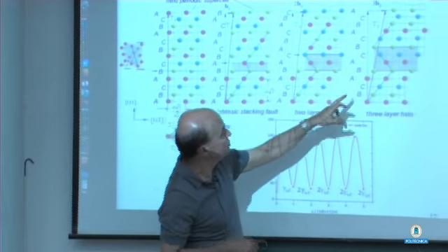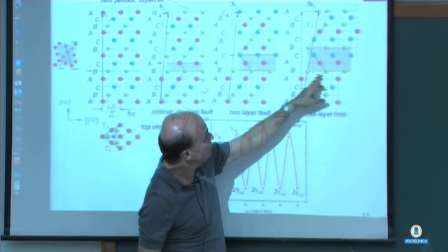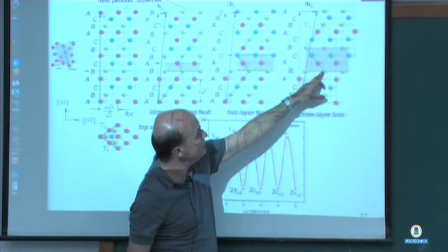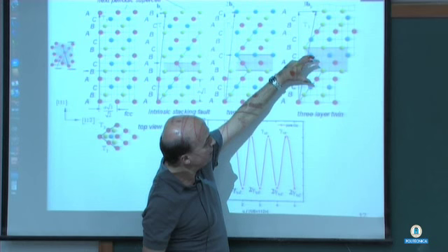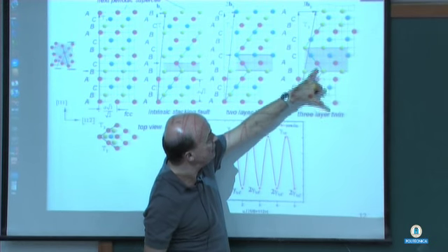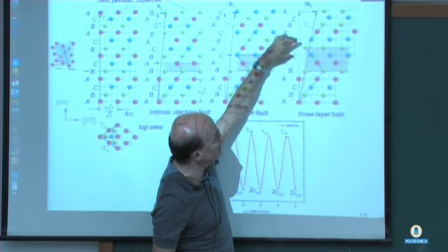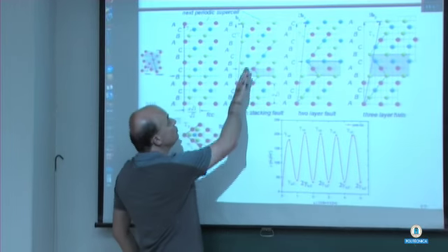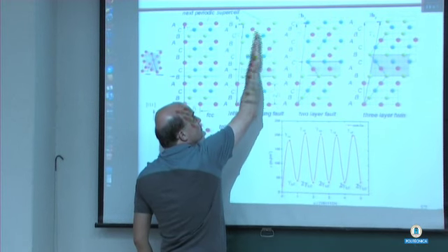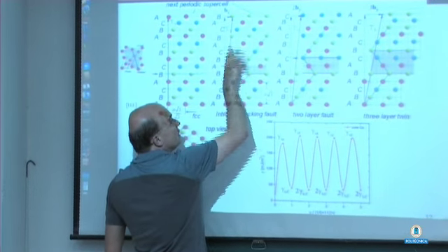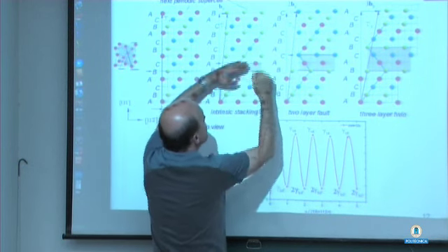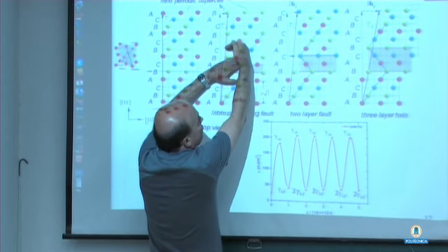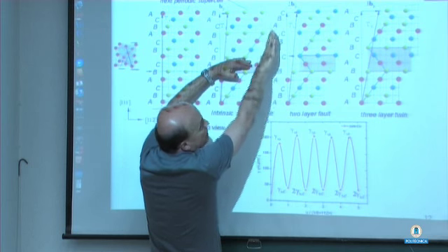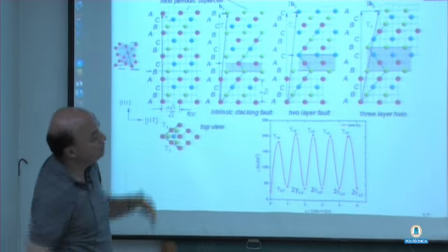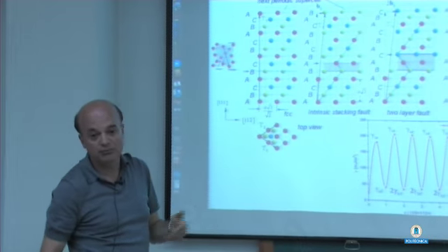And you could see here on the twin plane, this is the B, and there's symmetry along that plane. This is the A, that's the A, and that's B, and it is C and C on the side. And the way it's done is you move the entire row of atoms on top of this layer by Bp, and then the next one you move this entire layer of atoms above this plane by Bp this way. So you can create larger layers of twin.